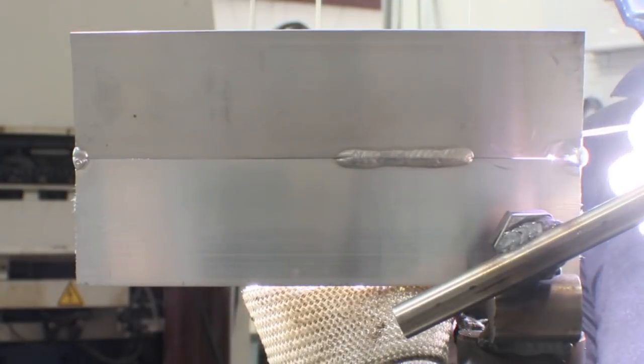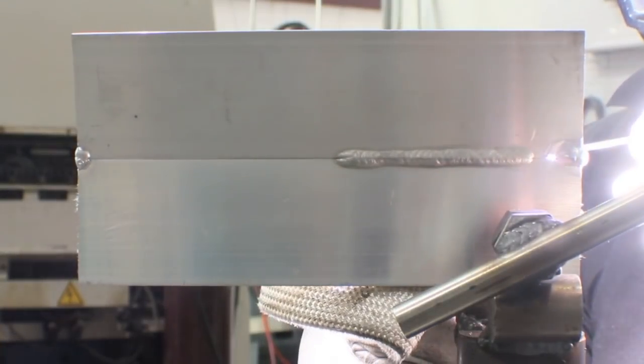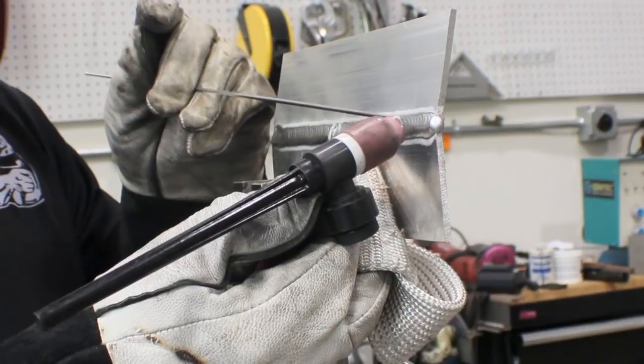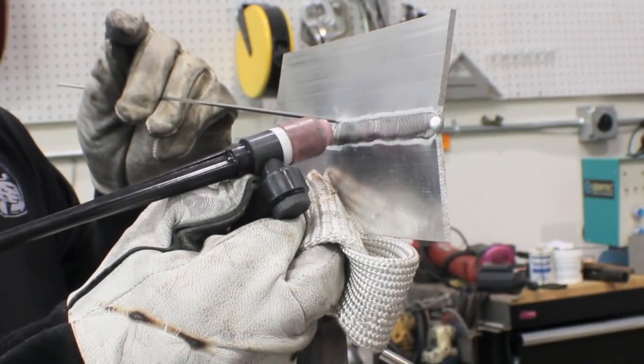You're not really seeing a puddle on the backside. You're pushing that puddle through, and that aluminum oxide on the backside is never really melting, but it is giving and pushing through. I always explain it to students like think of it like a peel coat, a coating, saran wrap or whatever. It pushes through on the backside, and the oxide film that's on the edges has a great effect on it also. You can see the tip of that electrode is rounded. I rounded it off using the AC balance set to the lowest setting. You can also just switch it to reverse polarity, but with inverters it's just easier to turn the AC balance down to round the tip. You can see a little line forming down the middle because there's oxide film on the sheared edge, and it's going to push it all the way to the back. You've got to get the heat right to where it pushes it and joins everything. Once again, this is the electrode angle that I use, pointing upward a little bit and adding filler to the top part of the puddle to kind of chill the top and prevent undercut.